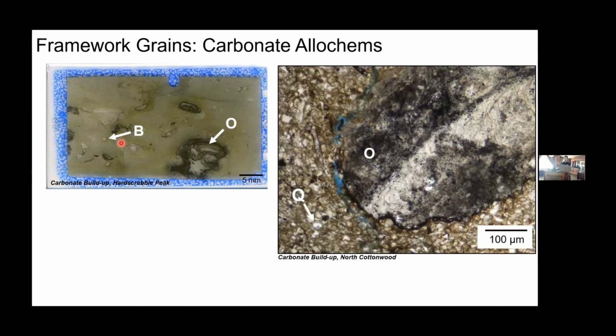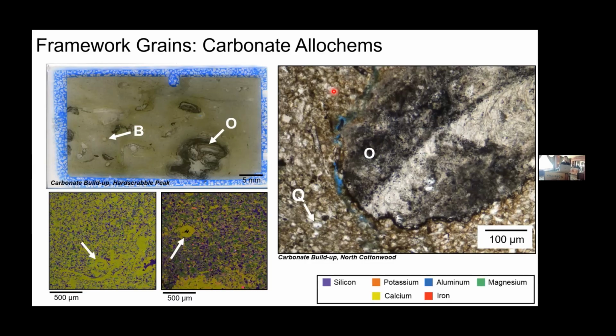Just looking at this in thin section, you can see an oncoid, or a larger oncoid here, but it's surrounded by a silty matrix that contains both quartz and feldspar, just like the framework grains we saw. Lastly, looking at this EDS, you can see that these carbonate grains, which are largely calcite, highlighted by these yellow areas here, are still easily recognizable. They have not been completely overprinted by diagenesis. You can still recognize these things in both thin section and in EDS.